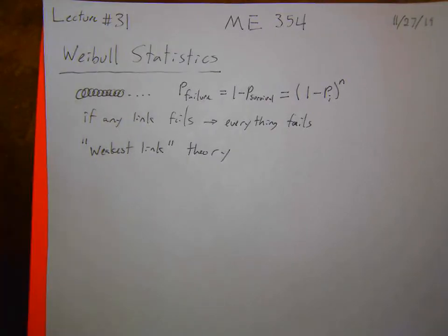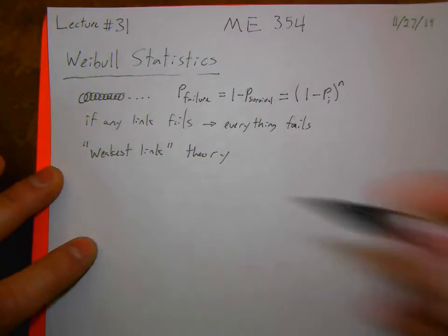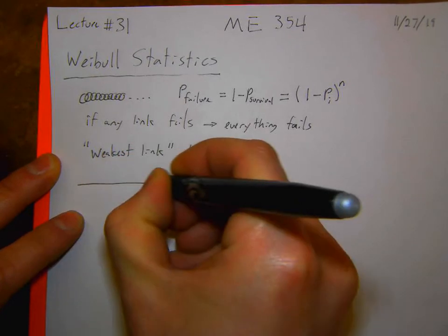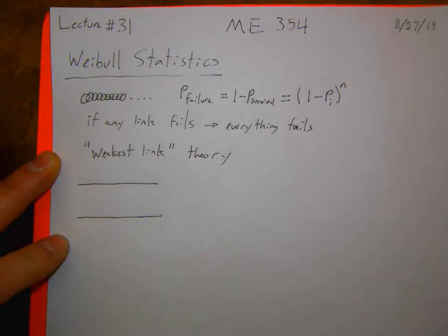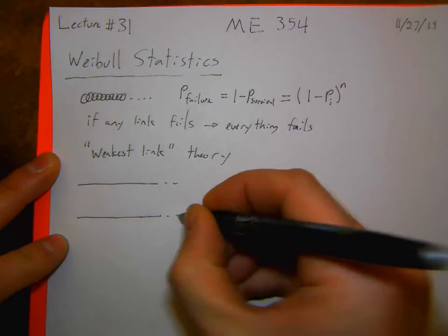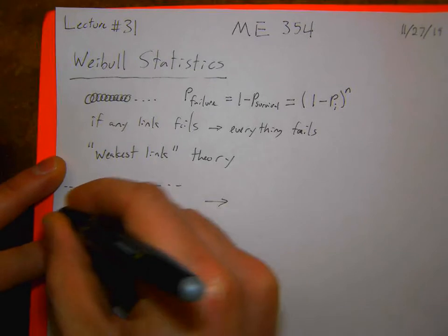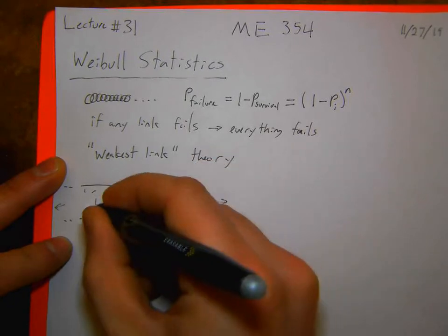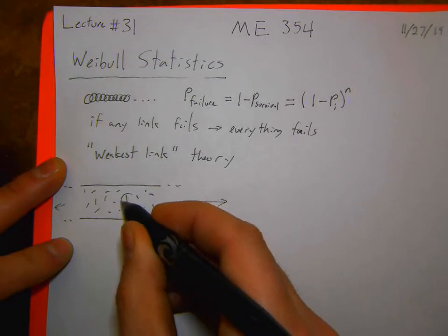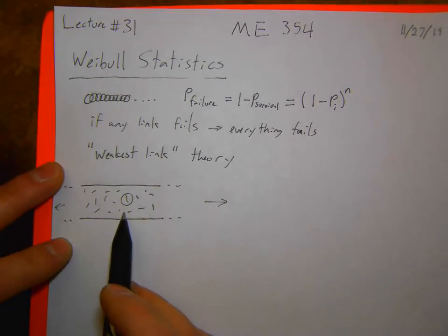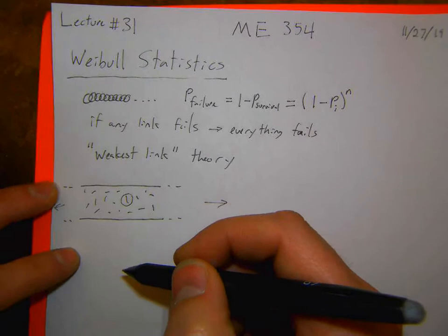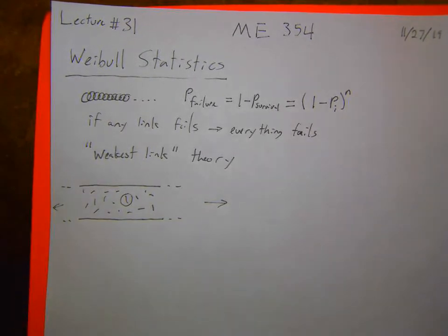So in brittle materials, the same type of idea applies. So if we now have, say, a carbon fiber that I'm pulling in tension, there's going to be some random distribution of flaws, some large, some small, all in different orientations. And then if in here there's some largest flaw that's going to act as a nucleation site, the failure of that flaw is going to cause this whole thing to rupture. And so now we can take a look at this. This is particularly for a brittle material.